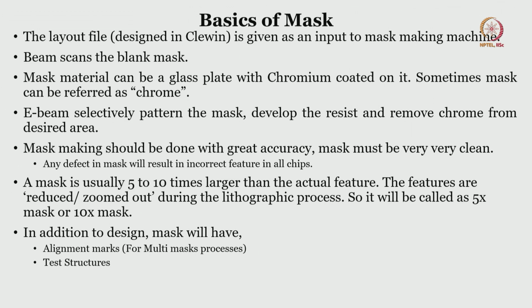E-beam selectively patterns the mask, develops the resist and removes the chrome from the designed area. So, the electron beam will selectively pattern depending on the type of pattern that you have designed using the Clewin software. Mask making should be done with great accuracy and the mask must be very clean. Any defect in the mask results in incorrect features in all the device chips.